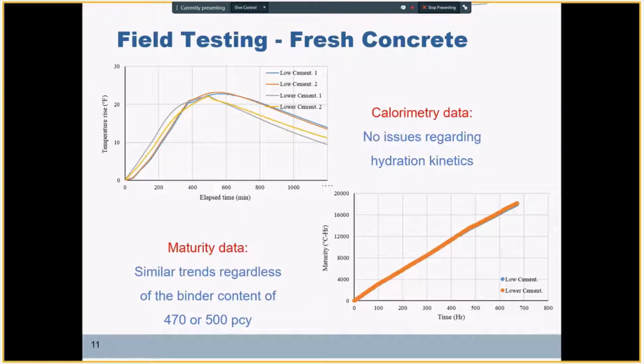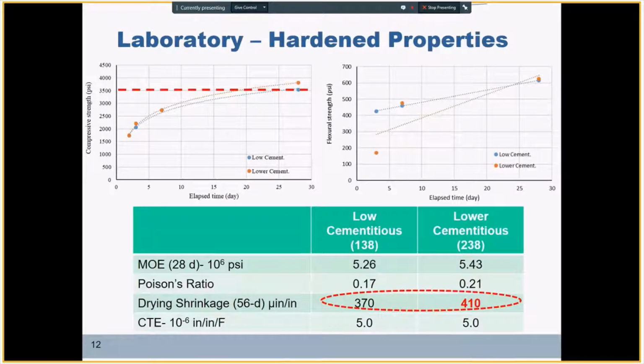The same with the maturity data, exactly similar trends regardless of the binder content. Same strength development behavior was expected for these two mixtures, which was also observed based on the mechanical property testing.